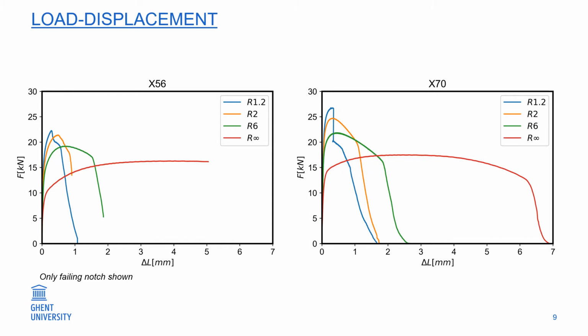A sharper notch causes an increased maximal load, but a decreased elongation, as expected. The most important thing to notice is a strange behavior for the sharpest notches in both steels.